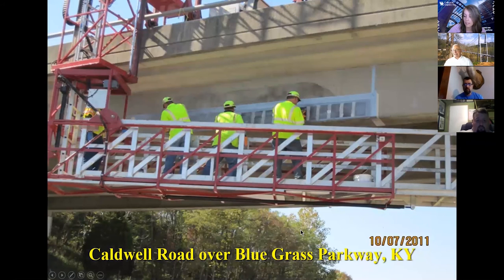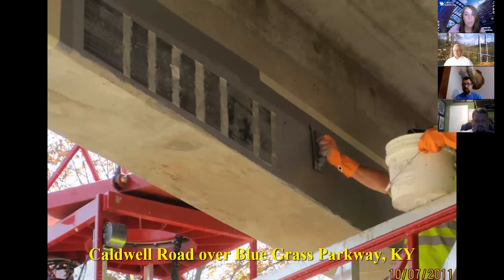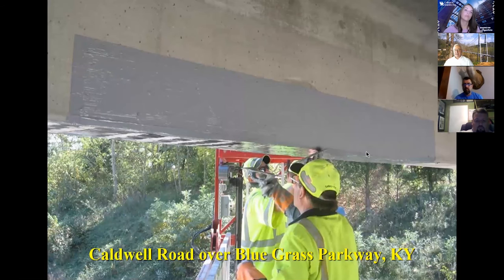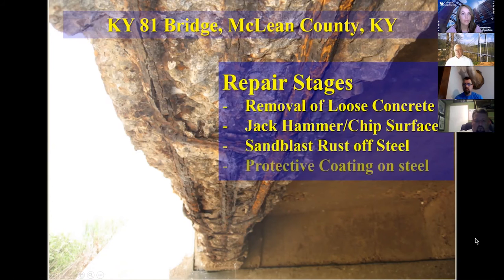So in this bridge, it had an impact, and one of the rebars was damaged. So basically what these rod panels do, they replace the capacity of the damaged rebars. And once we are done with it, you really cannot tell that it was repaired. I mean, of course, the gray here is not identical to the concrete, but as you're driving underneath it, you can barely notice it. This bridge is in McLean County.